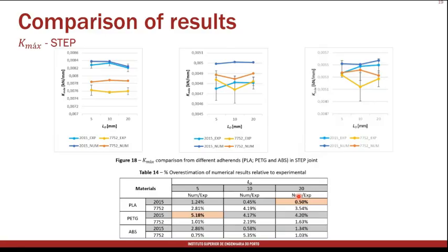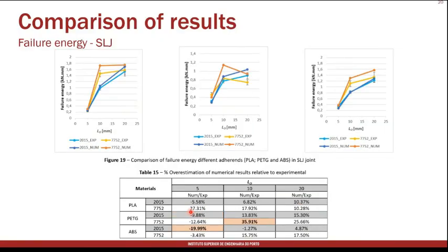In terms of step joint, also in terms of thickness, there are no significant differences, not a clear variation of increase or reduction with the overlap length. We have also significant deviations, specimens of the same conditions, tested experimentally, but here the maximum errors were not so significant as in the scarf joint. Finally, we want to evaluate the failure energy of the specimen, and this is the area beneath the